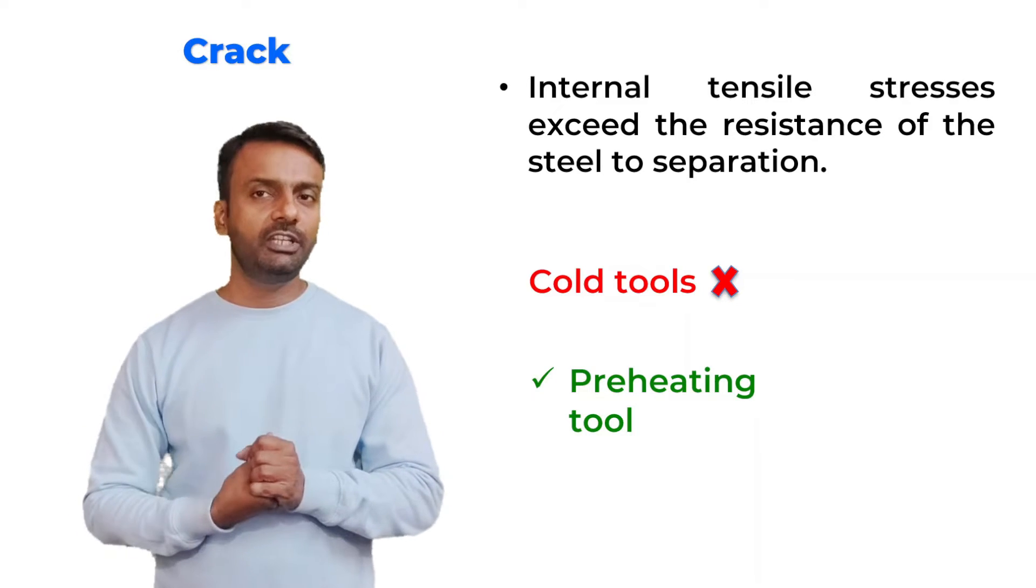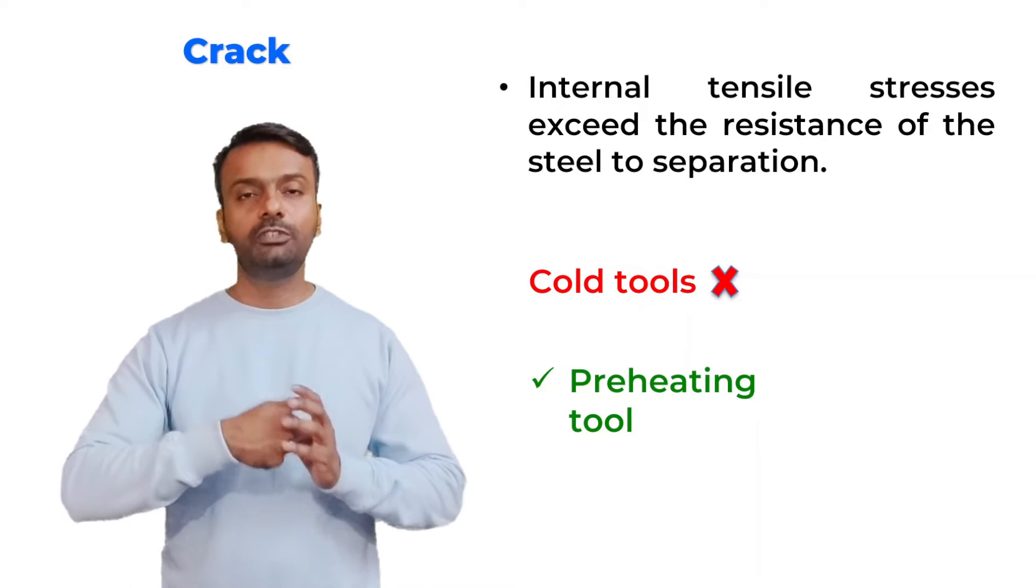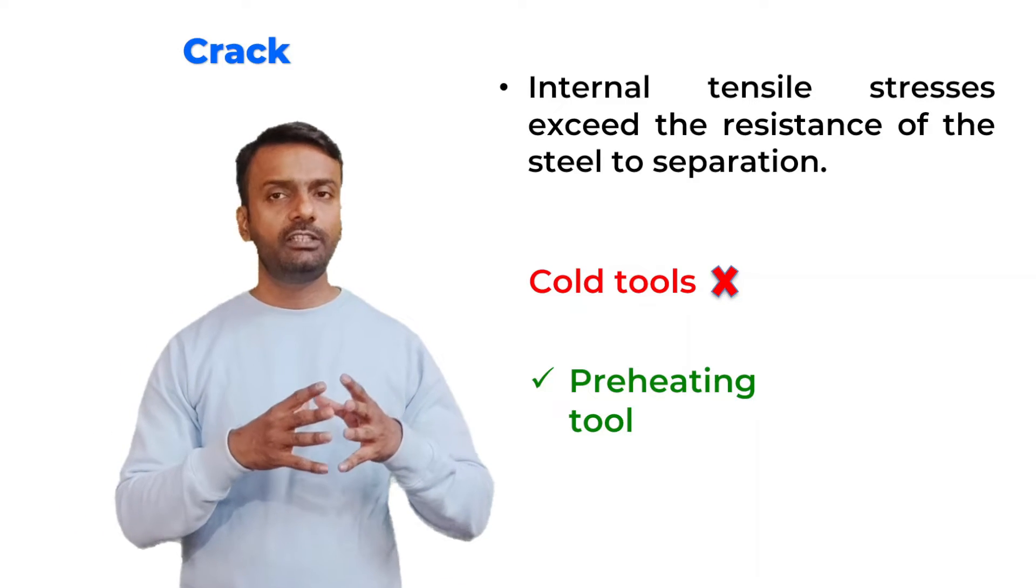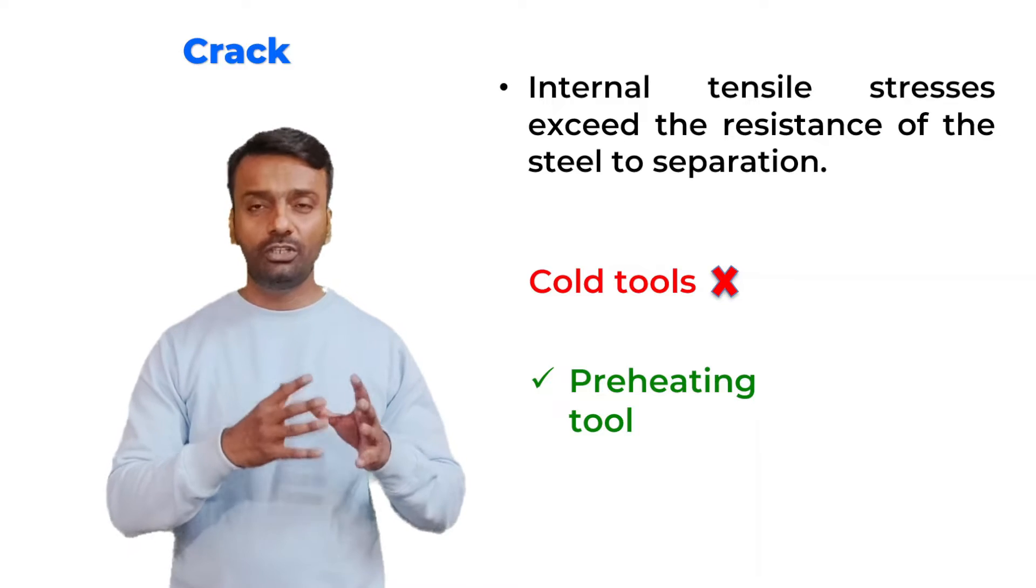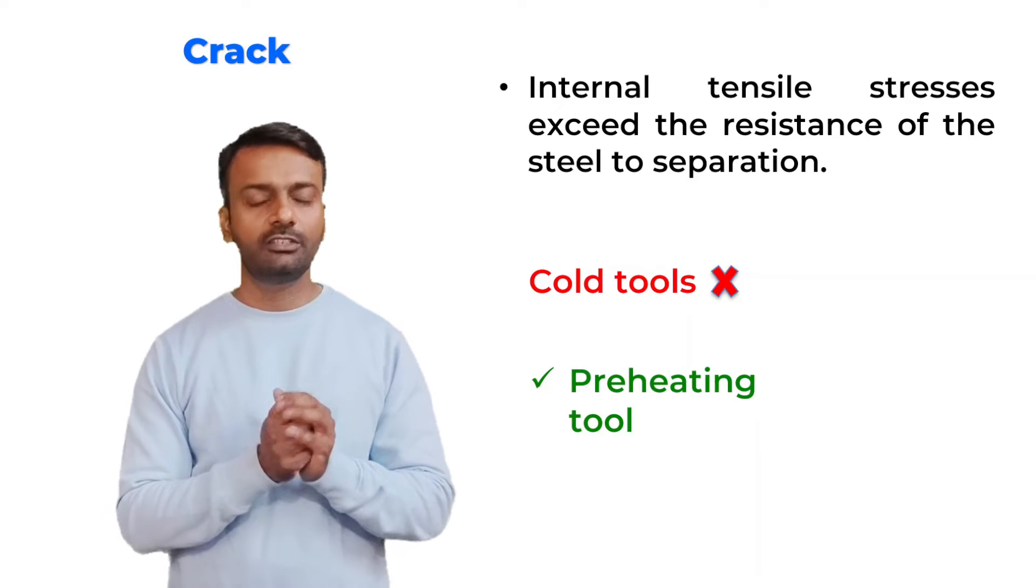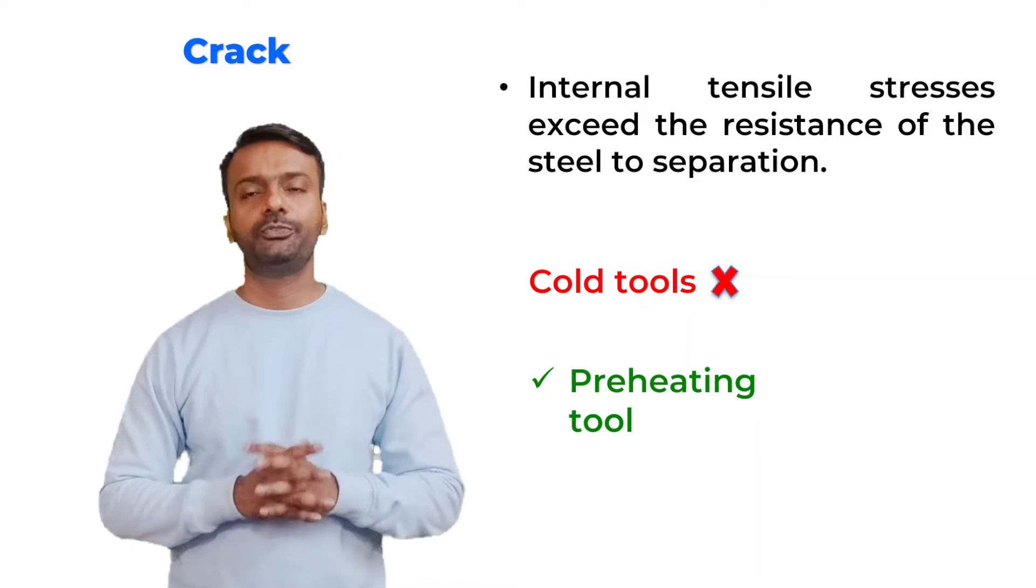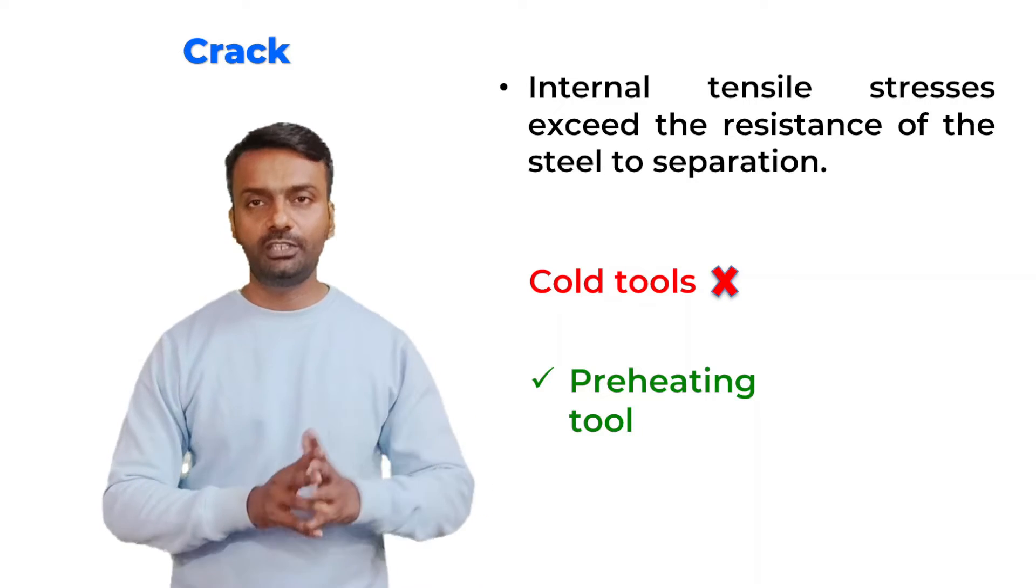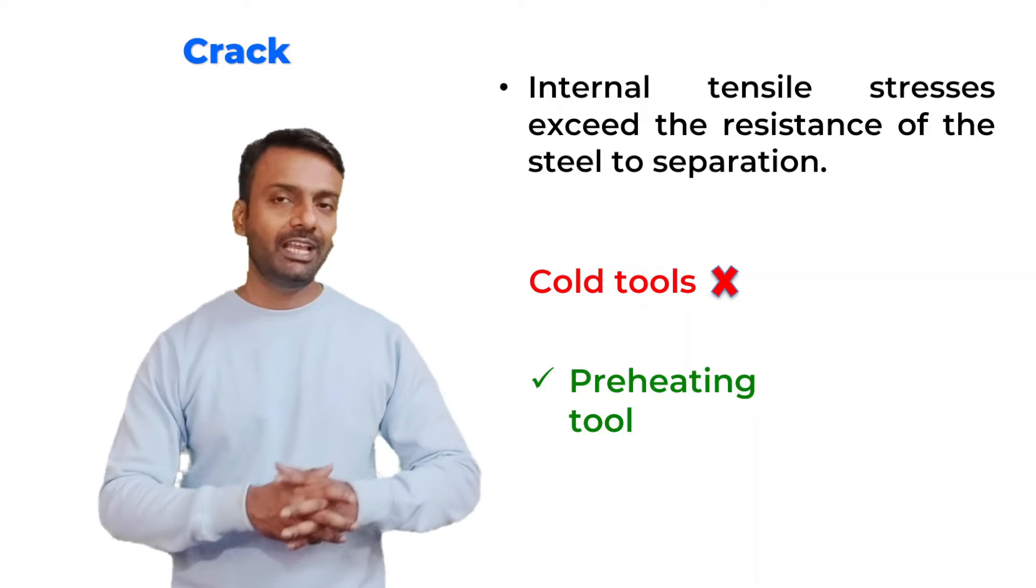The only thing which we can do here is that we can preheat the tool which we have. So when we preheat these tools, they will not create a temperature gradient when we are removing the sample out of the furnace and the temperature will almost be the same. It will not be quenched immediately which will make them more crack prone.